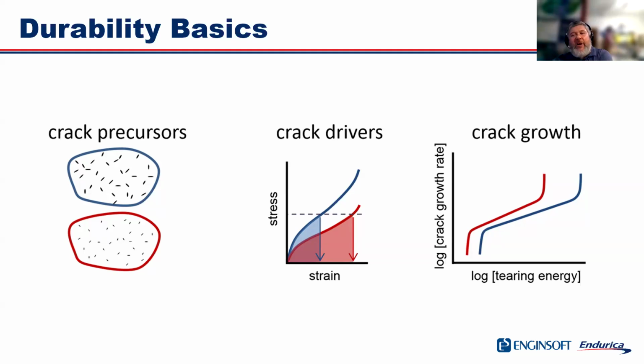So from day one, you've got these crack starters, crack precursors in the material, and then the next thing we have to think about is crack drivers. So you've got these small features, they concentrate stress. And then under the loads that you apply to your part, those small cracks begin to grow. And so we need to quantify the crack drivers. They're related to the stress strain behavior. We use a parameter called the tearing energy or the energy release rate, right? For those who may be familiar with fracture mechanics, it's kind of an idea from that field, the tearing energy. But obviously, bigger tearing energies lead to faster crack growth. Smaller tearing energies lead to slower crack growth. And so, we need to quantify what's the magnitude of the crack driving force.